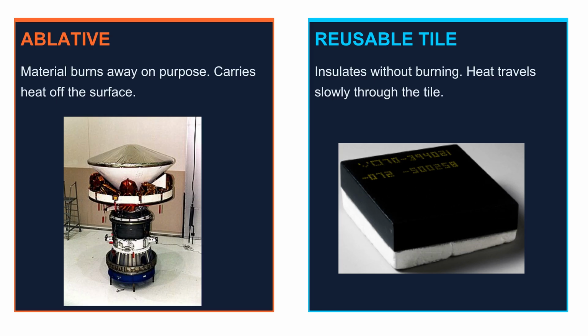Thermal protection systems fall into two categories. Ablative shields sacrifice material deliberately. The outer layer chars, melts, and vaporizes. That phase change process absorbs enormous amounts of heat and carries it away from the surface. One use only. Reusable systems insulate without burning away. The material absorbs very little heat and conducts it slowly enough that the structure stays cool. Multiple uses, but more complex to maintain.